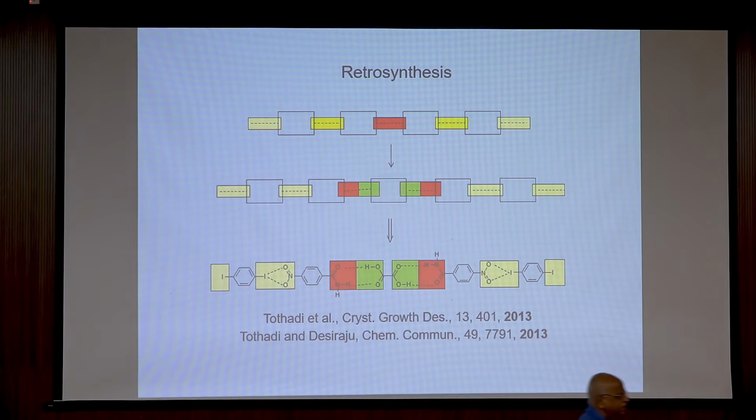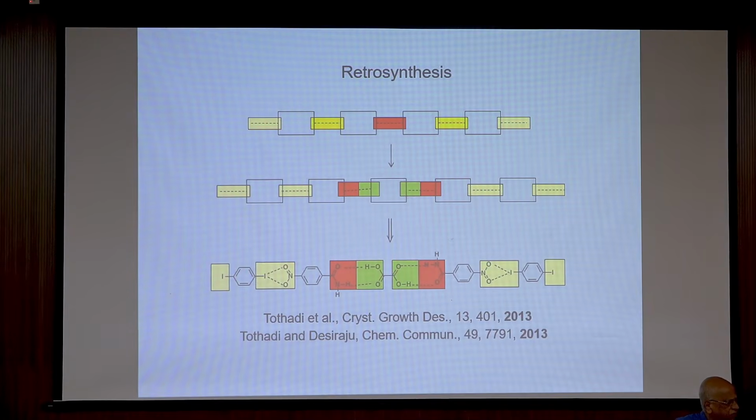Now why is this an important problem in crystal engineering? Because crystallization is always a purifying technique. You take brine or you take molasses, you get a pure crystal out of it. Crystallization is an excluding phenomenon. It throws everything out, because the tendency to form a single component crystal is very high. So when I am trying to put 2 and 3 and all into the same crystal, I am fighting against something. That is the synthesis part. Trying to make these kinds of things becomes more and more difficult. So like that I can go on and on.